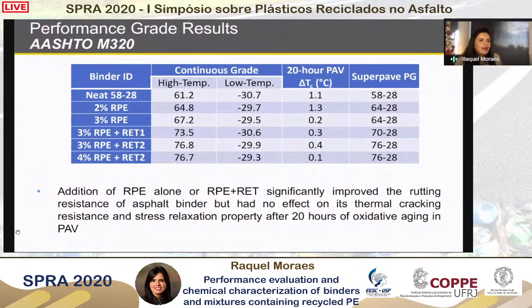And here we have the performance PG grade results, Superpave PG grade results, with standard PAV aging of 20 hours. And we have the high and low temperature continuous grade of the neat binder, the neat containing plastic only, and the terpolymers. And these are only the 5 binders that were screened previously using the softening point results after storage stability.